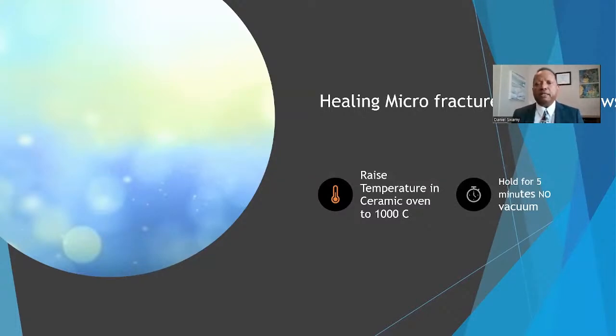So I advocate raising the temperature to about 1,000 degrees, placing your units into the ceramic oven, and then raising the temperature to 1,000 degrees and holding it for 5 minutes with no vacuum. What this does is seal all the microfractures that you cannot see with your eyes, and you do this prior to glazing. If you're adjusting in the operatory and you're seeing sparks fly, it's really useful and helpful if you can reseal the zirconia using this process.